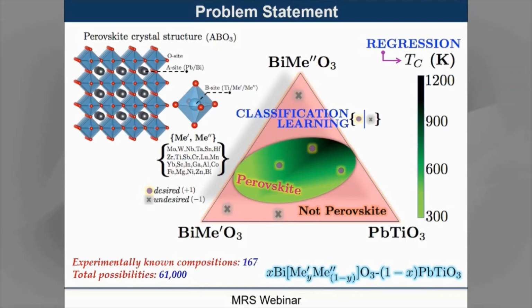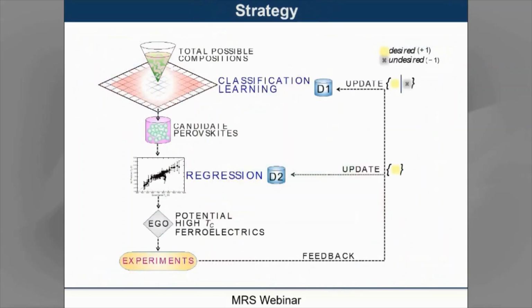Are there new high-temperature ferroelectric perovskites in this unexplored space? And can we use machine learning type of methods to rapidly navigate this space and identify new materials? And for this problem, we devised a new strategy, which we refer to as a two-step approach to accelerate discovery. The first step here would involve an independent machine learning model, a classification learning model, that will allow us to screen for compositions that are formable in the perovskite crystal structure.